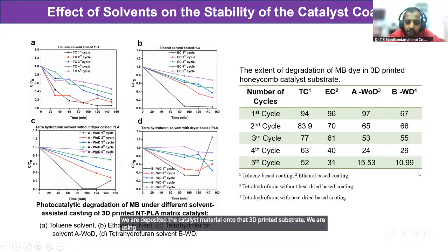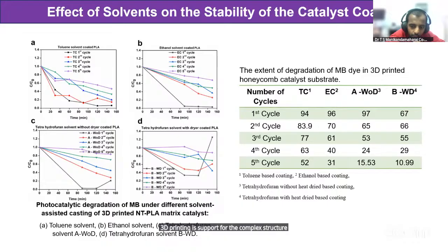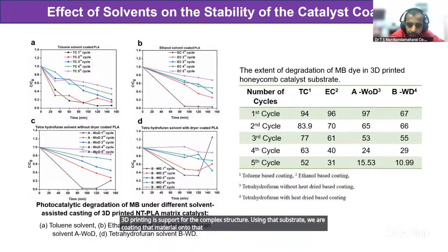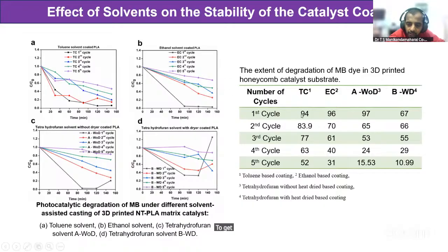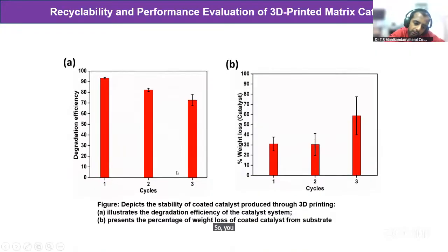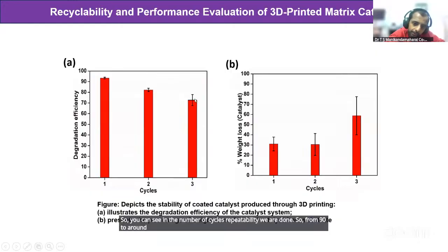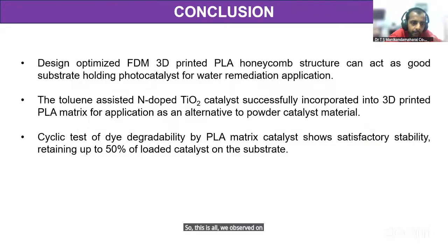With this, the number of cycles and repeatability is increased. That is the advantage of the 3D printed substrate. 3D printing supports complex structures. Using that substrate, we coat the material onto it and run a number of cycles. From the first cycle to the fifth cycle, about 50% degradation we are attaining multiple times. So you can see we have done the cycle repeatability. From 90 to around 70% in the third cycle we are getting. With respect to that, the coated material is removed from the substrate. Also, losses are there. So these are all we observed on the performance of the material.